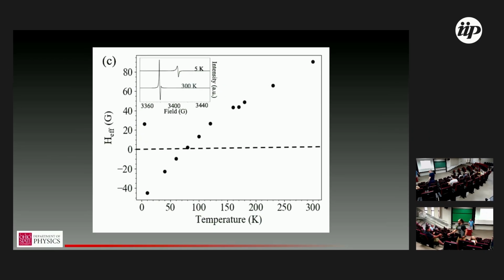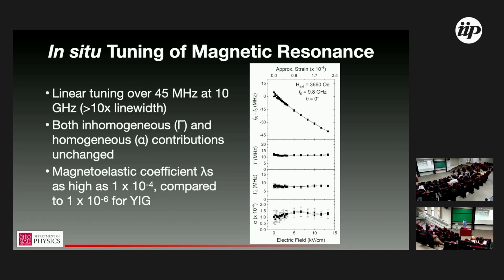So the strains you can apply by making it cold and taking advantage of the difference in thermal expansion coefficient is much larger than you can apply with the piezo. Yeah. So the piezo is just in that sort of upper range. And like the simple benchmark is with temperature we can go through 0, and we're nowhere near that with the piezo. So this is normalized as a shift from equilibrium, but it's about a 40 megahertz shift on a 10 gigahertz line. So it's a pretty modest change.